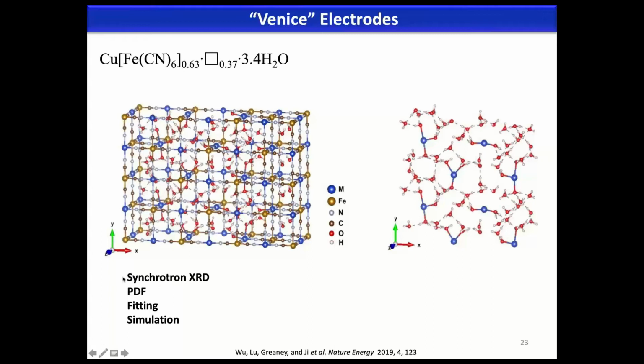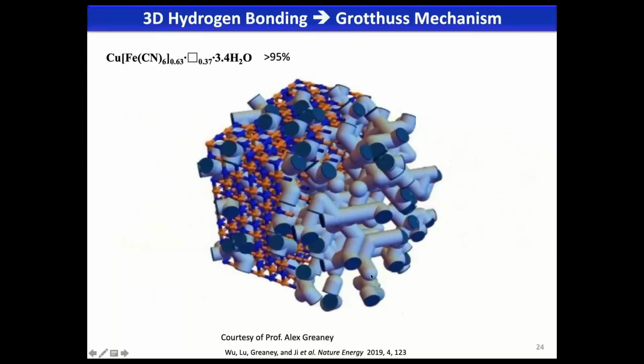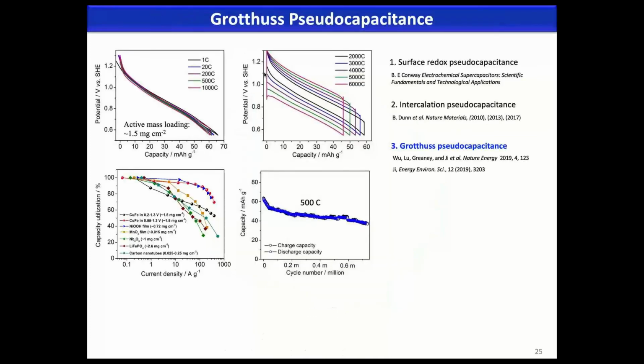And by the way, we made a painstaking effort to characterize the Prussian blue we had. We have done PDF based on neutron scattering, and synchrotron work with our collaborator at Argonne, Dr. Jun Lu, and Dr. Jörg Neuefeind at Oak Ridge for the PDF. Then Dr. Greaney computed the continuous structure of water. We found that 95% of water molecules are talking to each other by hydrogen bonding. That's great. This gives us the confidence that we will probably observe something really fast.